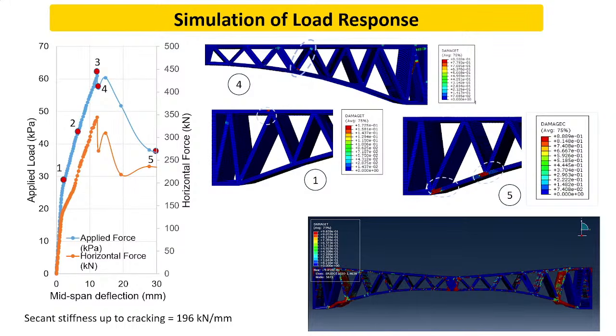And that's what's happened. So if you look at point 1, that is where the first crack happened. And after the cracking, the steel takes the tension. The residual stress is small, but it still takes it. And because of that, there's a redistribution of stress within the entire lattice structure. And that allows the load to build up to a significantly high value. So while the first cracking happened at 30, it essentially failed at almost double that load.